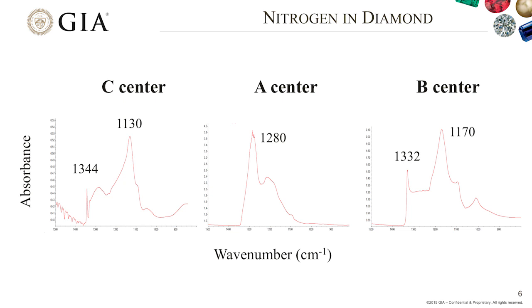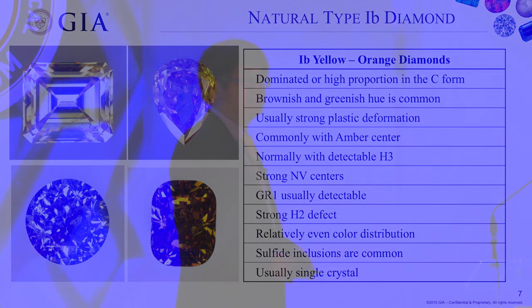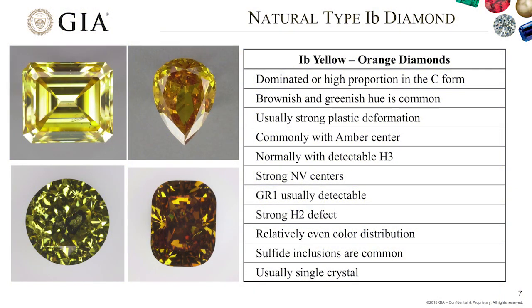There are some diamonds where isolated nitrogen is the dominant form of nitrogen impurity — that's the C form — and we call these Type 1b diamonds. Natural 1b diamonds are yellow, but different from what we might expect: they have a very strong brownish and greenish hue. These stones are dominated by isolated nitrogen but could show some aggregated A-form nitrogen. The distinctive brownish-greenish color comes from plastic deformation, which I'm going to discuss extensively in today's presentation. They have very strong plastic deformation that affects their gemological properties.